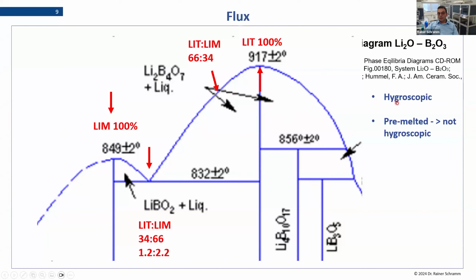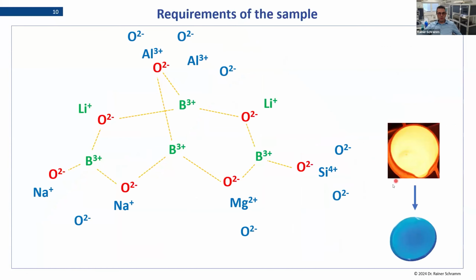Of course, the lithium borates from nature are hygroscopic, but if we pre-melt them, that means they are once melted into glass and then ground again, then you reduce the surface, and in this way they are much more stable and you can directly use them from the bottle. And of course, nowadays we also have dust-free fluxes, which are even healthier to use. And these, for example the bead fluxes, you can also use in dosing systems.